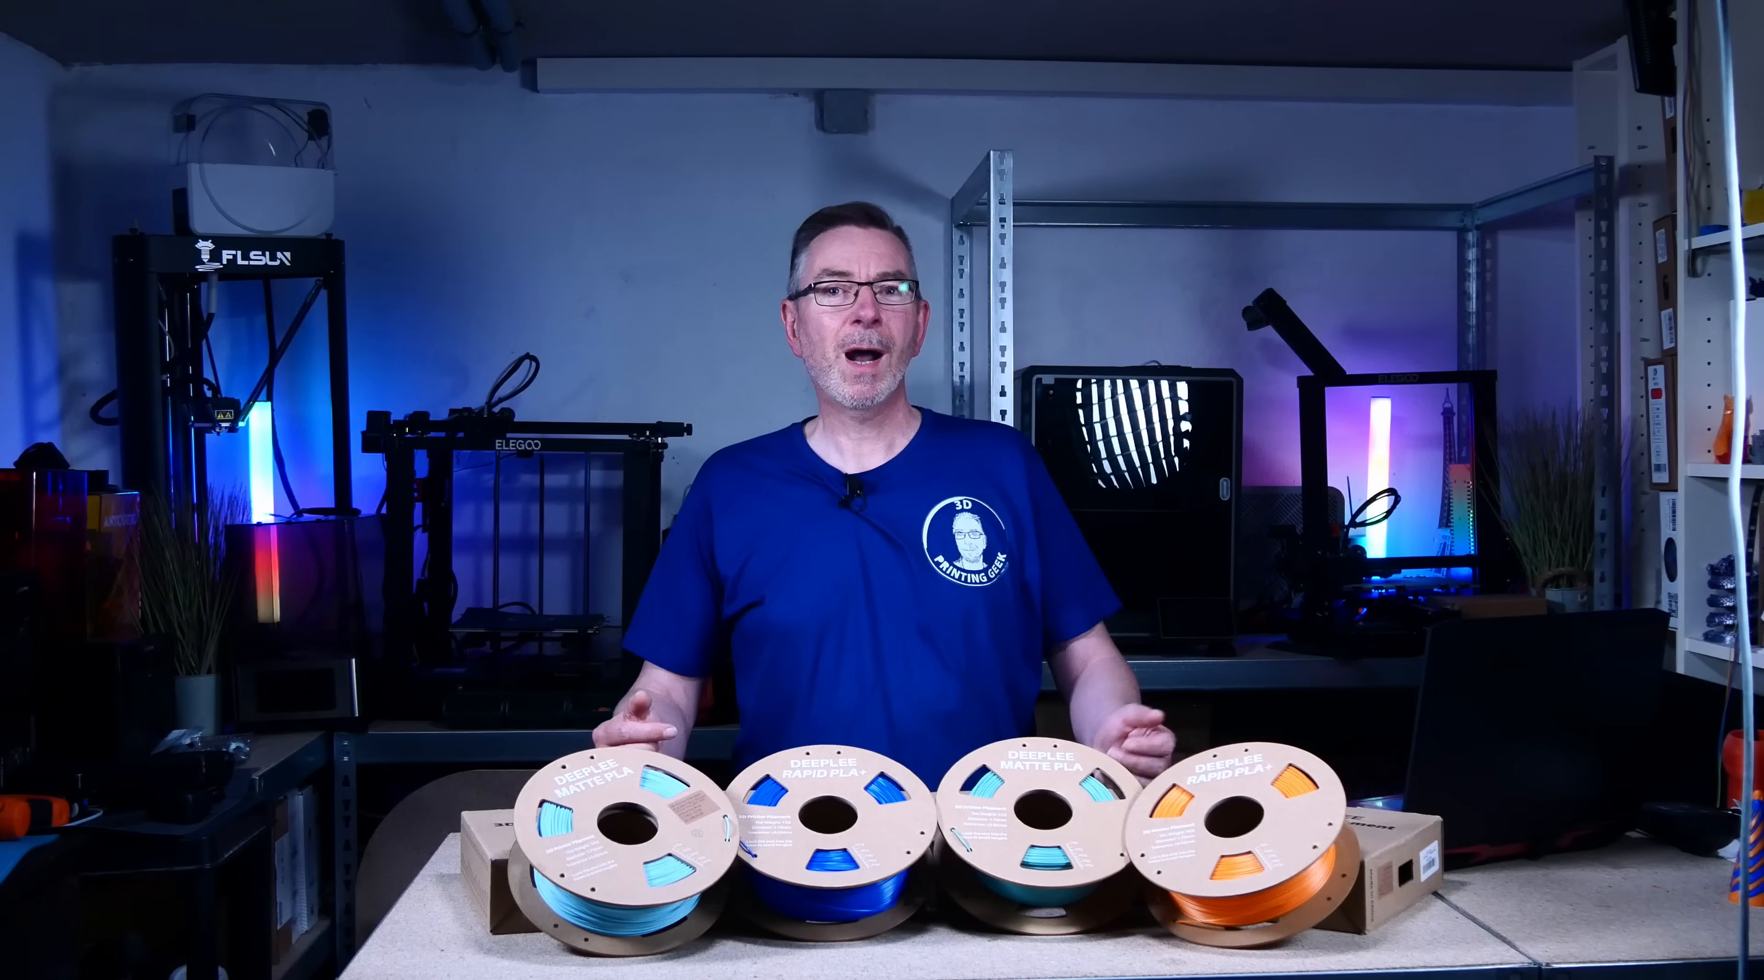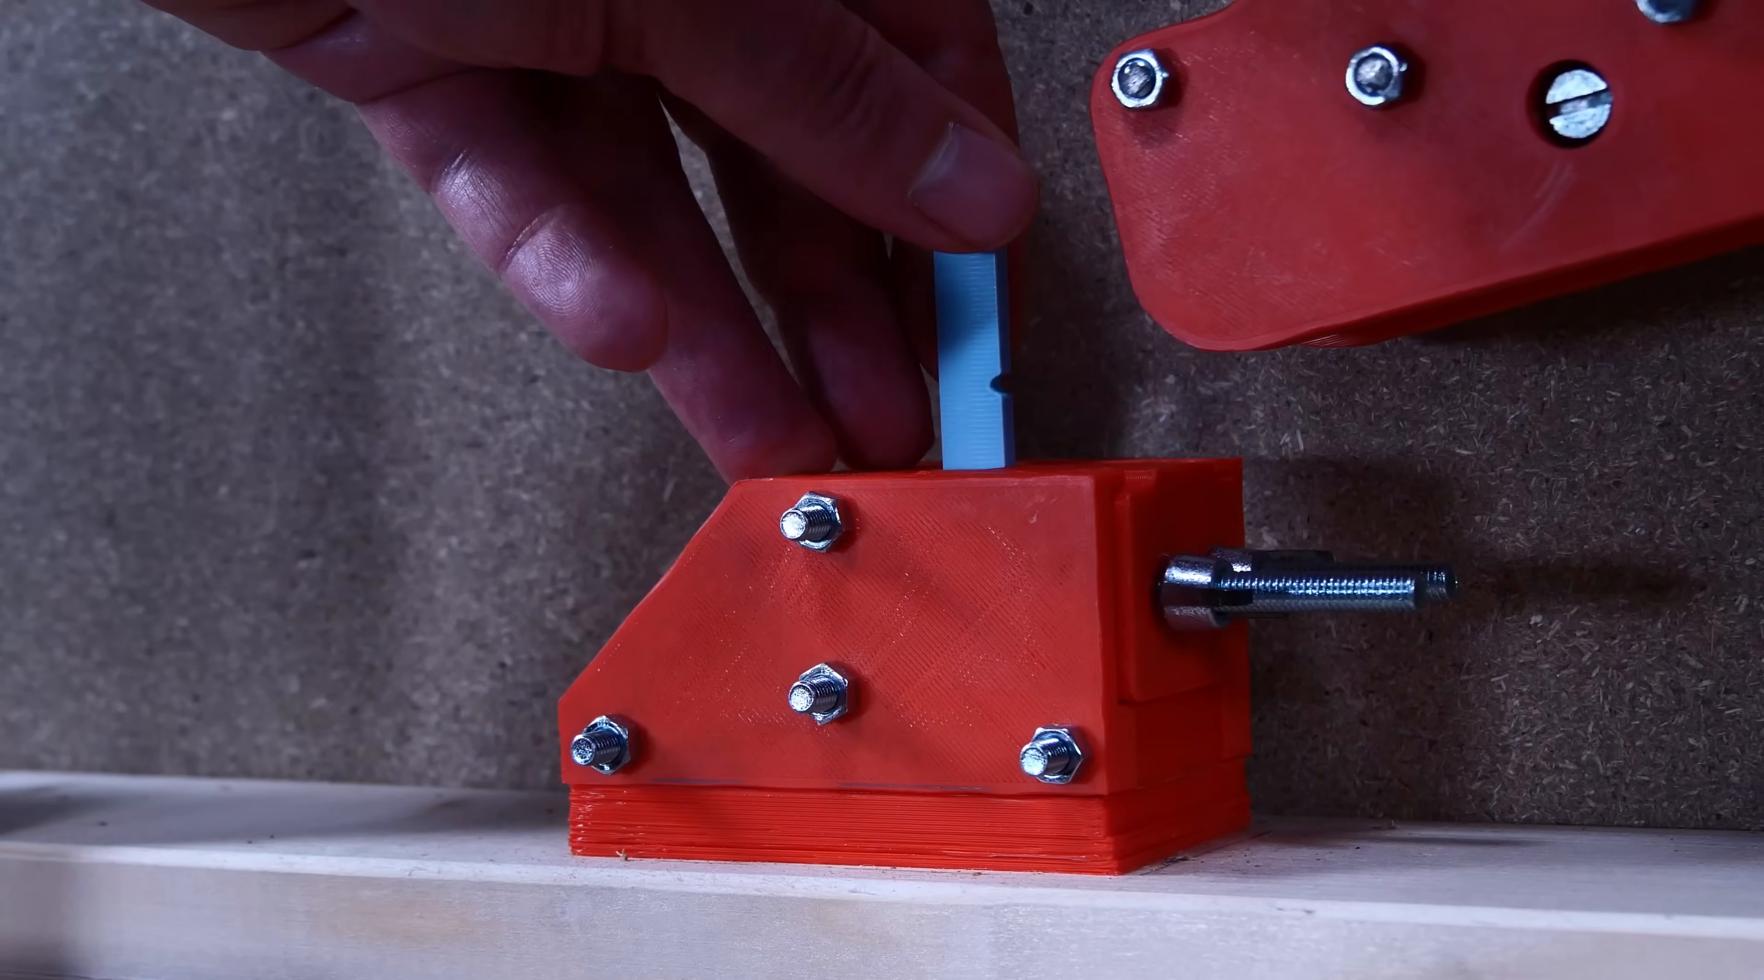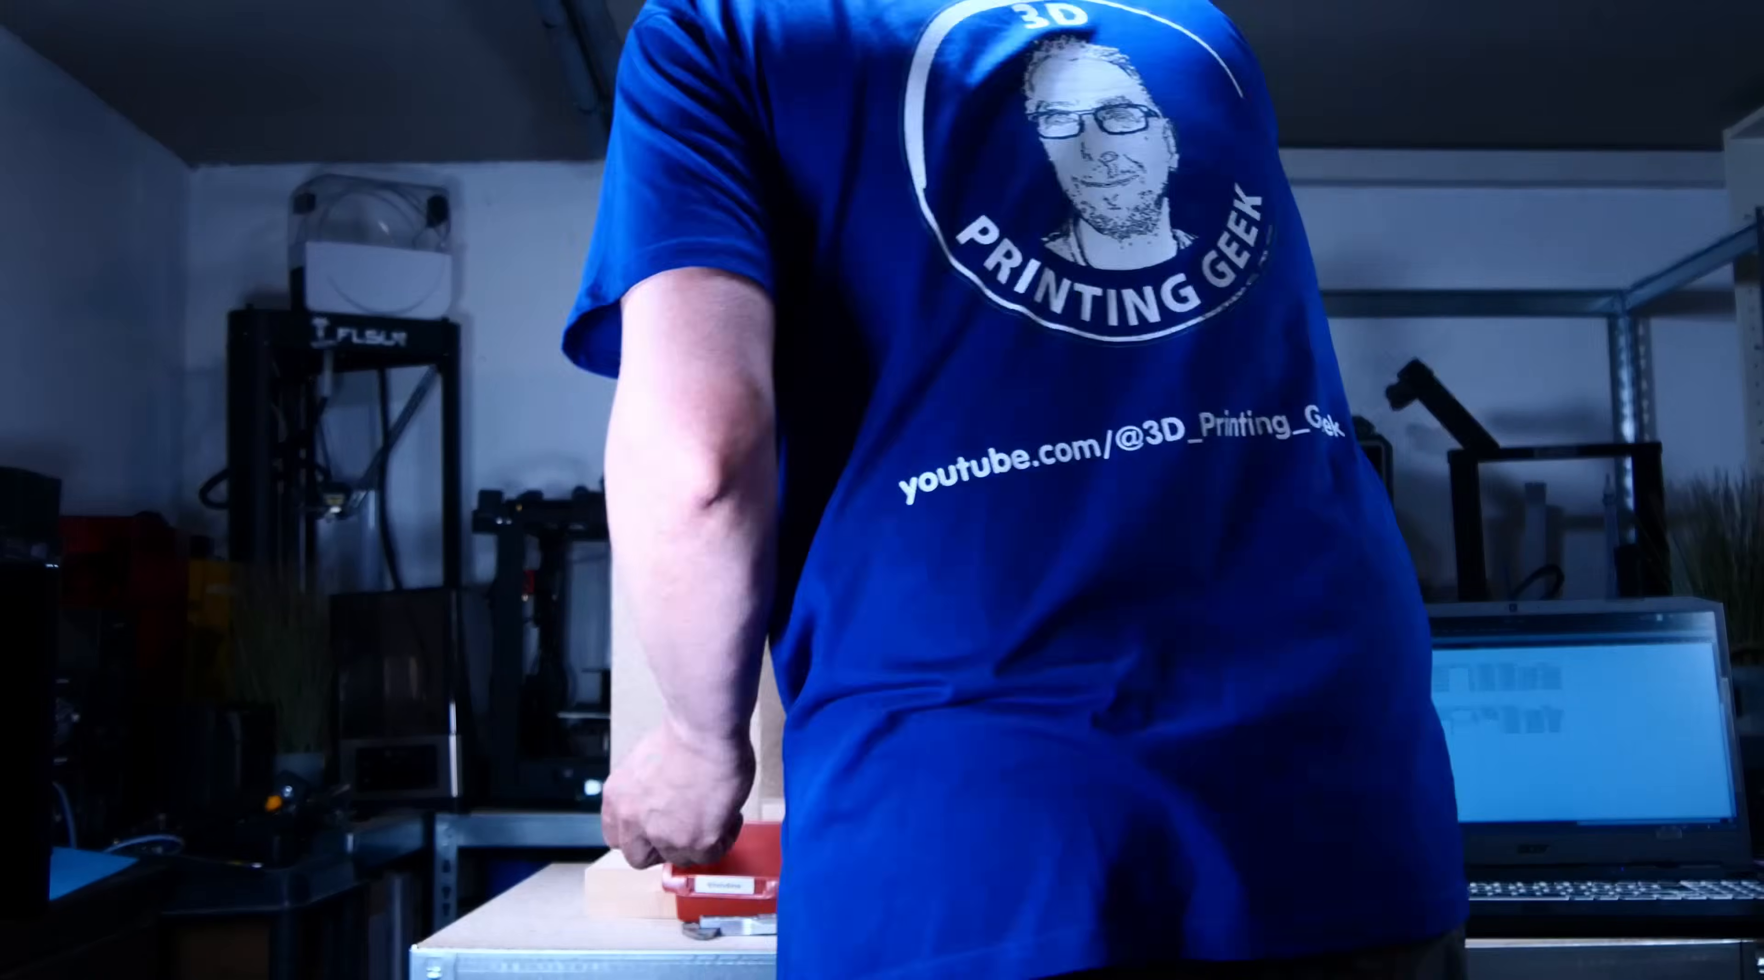Time to bring up the IZOD tester, which I closely built after CNC Kitchen's machine. So hopefully we'll get results that can be compared to his results. With each filament, I printed 10 test specimens, 5 lying flat and 5 vertically. I increased the shell lines until no infill was needed. I then tested each filament, fixing them in the vise, resetting the drag dial to its initial position, and releasing the hammer from the top position.